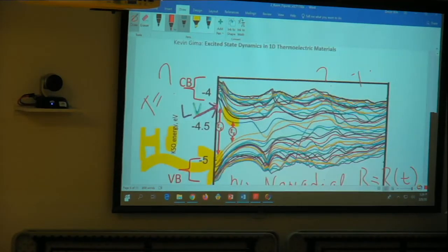When the change of energy of orbital versus time is flat, it is not an immediate connection, but it is a signature that non-adiabatic coupling between these orbitals is expected to be small. In this energy range, the HOMO is not changing much in time, and the LUMO is not changing much.